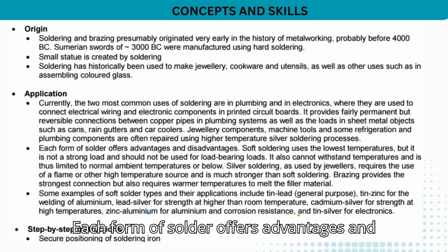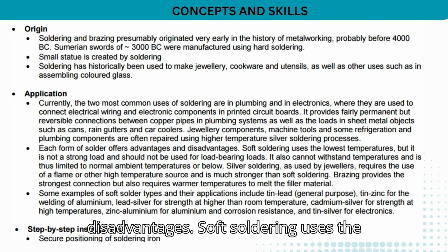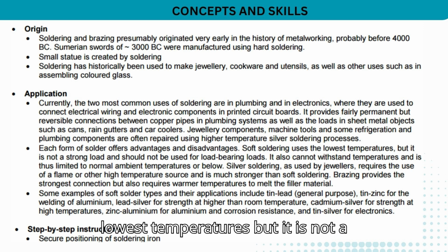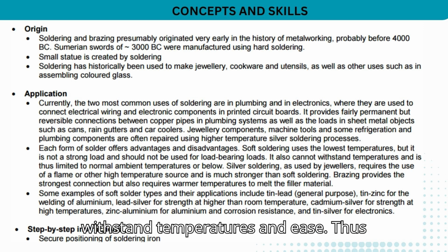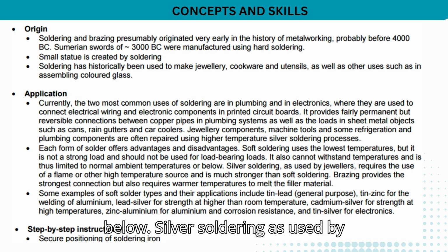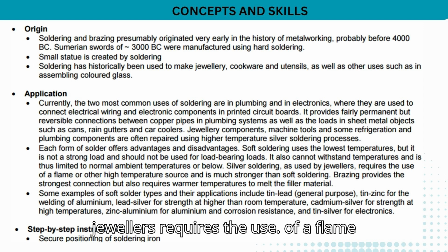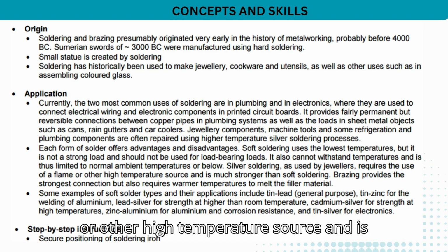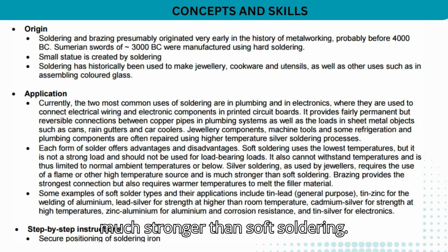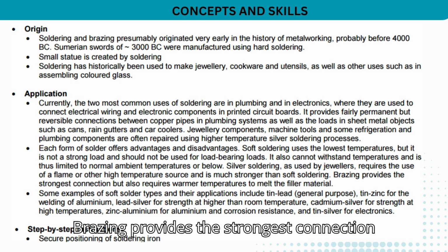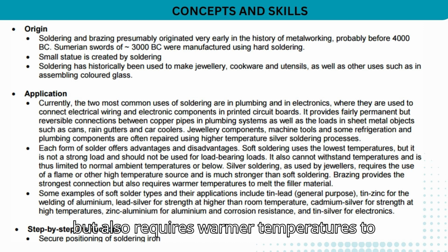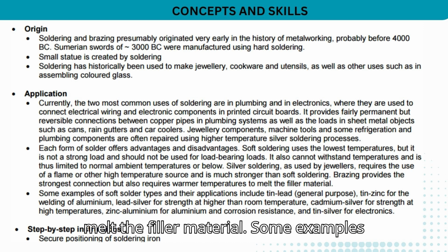Each form of solder offers advantages and disadvantages. Soft soldering uses the lowest temperatures, but it is not a strong joint and should not be used for load-bearing joints. It also cannot withstand high temperatures and is thus limited to normal ambient temperatures or below. Silver soldering, as used by jewelers, requires the use of a flame or other high-temperature source and is much stronger than soft soldering. Brazing provides the strongest connection but also requires warmer temperatures to melt the filler material.